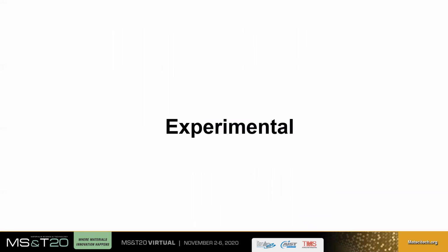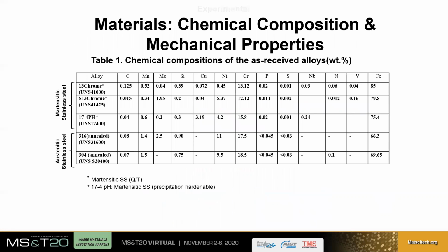So let's discuss briefly the experimental section. In this study, we selected 5 different stainless steel materials. These alloys are extensively used in downhole service and permanent tools. 13 chrome, super 13 chrome and 17-4 PH stainless steel are martensitic stainless steels, whereas 13 chrome and super 13 chrome are quench and tempered stainless steel, and 17-4 PH is precipitation hardenable steel.